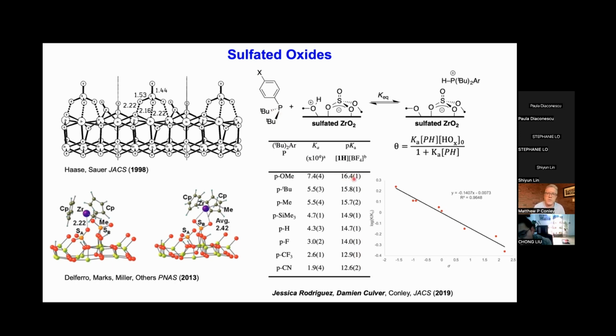So that's a solution measurement. And then we see that as we decrease pKa, the association constant of the phosphine goes down, which is exactly what you expect for a weak acid interacting with a weak base. If sulfated zirconia was behaving like a superacid, we would expect irreversible binding for all of the phosphines studied here. And something that I think is kind of neat: I told you a couple slides ago you can't really apply Hammett acidity type models to understanding surface acidity. But in this case, because we were slurrying these materials in acetonitrile, we have very nice linear, Hammett-type behavior for phosphine binding to the sulfated zirconia surface.